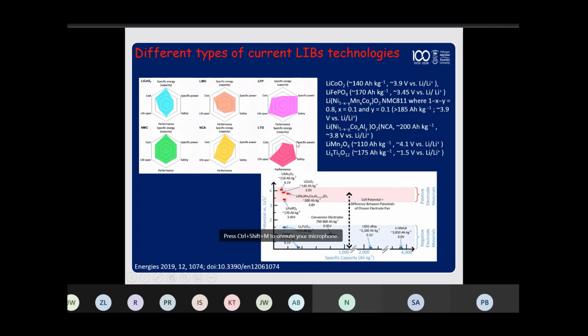In terms of anodes as well, so active materials used for the negative electrodes, the most famous, of course, is graphite, which is the one that is most used. However, there are other types of active materials that you can use for the anode. A typical one is lithium titanate. This is because it has a high potential compared to lithium, and it is extremely safe to use because it avoids some of the most important degradation mechanisms.